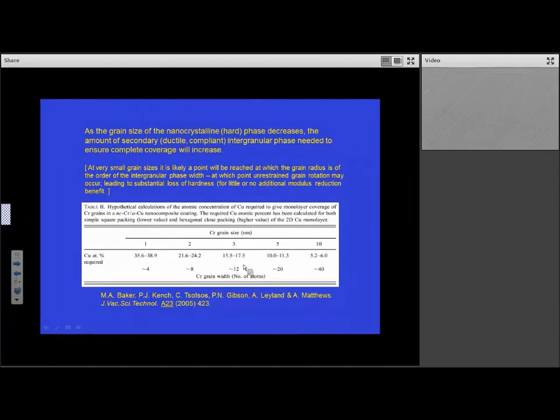One aspect to consider is the amount of soft phase that you need. And this depends on the grain size. So this is the chrome grain size coming down from 10 down to 1 nanometer. And you can see that as you reduce the grain size, in order to have a complete coverage of the grain, you have to go to very high copper content. So there are limits. And if you go to too small a grain, you run the risk of getting grain rotation and no longer getting a hardening effect. So there is an optimization to be done on these metal nanocomposite coatings.